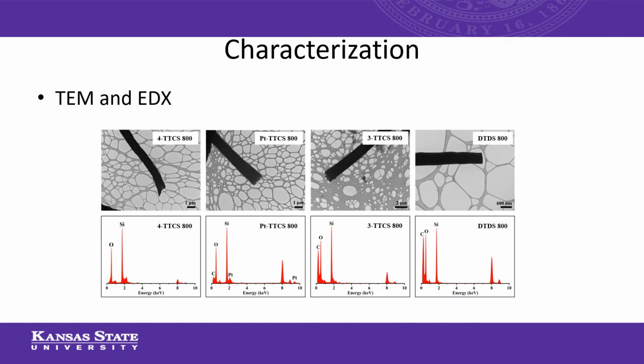This slide shows some TEM images and EDX information. The TEM shows pretty much the same information as the SEM. You can see the diameters are at maximum 2 microns down to 600 nanometers. And one thing to notice is that platinum signals are detected in platinum TTCS even after pyrolysis.